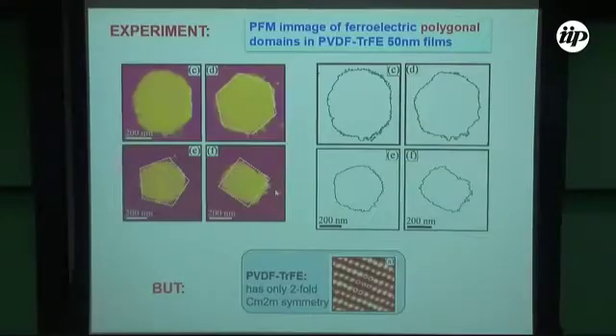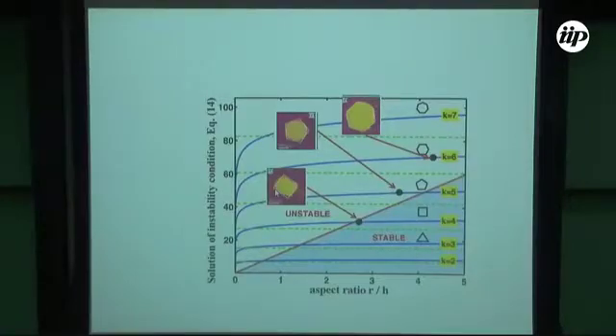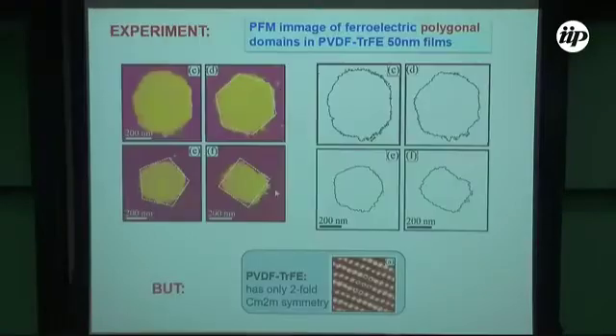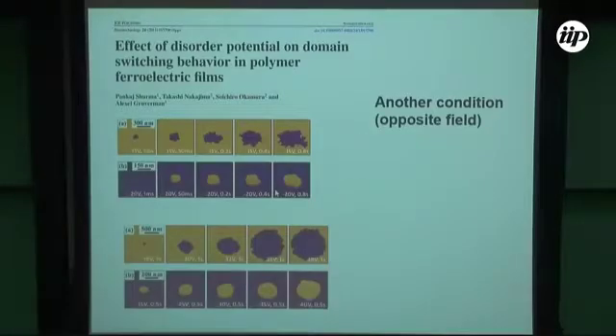After this, the experimentalists were looking, and indeed they found 4 and 5. So this is the result. For the given aspect ratio, they really found another. They looked more attentively at the experiment, and they also found a different type of instability. So 6 is not a magic number, at least in this theory, but we see that electrostatics alone can play a lot in the physics of ferroelectrics. Moreover, we have instability towards breaking of the initial circular symmetry.